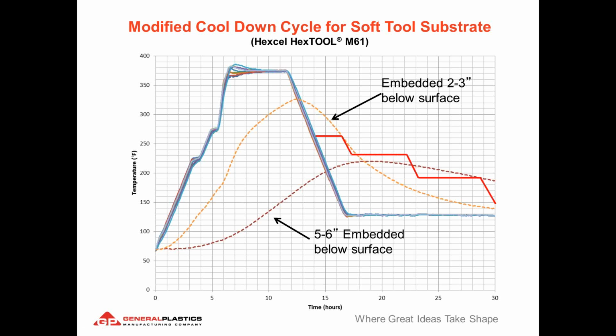But if you want to use the foam again, we recommend some step down, which basically equilibrates the surface temperature of the foam with the inside of the foam to try to match the thermal expansion closer so that we don't get surface cracking and your foam can be reused again. What that does is extend the time of your cure cycle. So again, these are things to discuss with your supplier and also do some prototyping ahead of time.